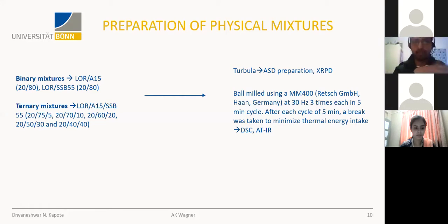Then I made some ternary mixtures to see if we can achieve our goal. Loratadine, Affinisol, and shellac were mixed together because we assumed that, due to shellac's low molecular weight, it has a higher tendency to get mobilized with HPMC and can form a uniform matrix that can be easily extruded, as well as spray dried. So we prepared ternary mixtures in a ratio like 20-75-5, where 20 stands for API, 75 for Affinisol, and 5 for shellac. We varied the ratio of Affinisol and shellac to see whether we can modulate the dissolution profile. We prepared these via Turbula mixer for amorphous solid dispersion preparation and also for spray drying.